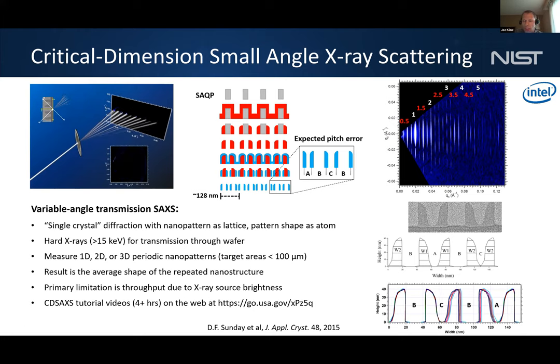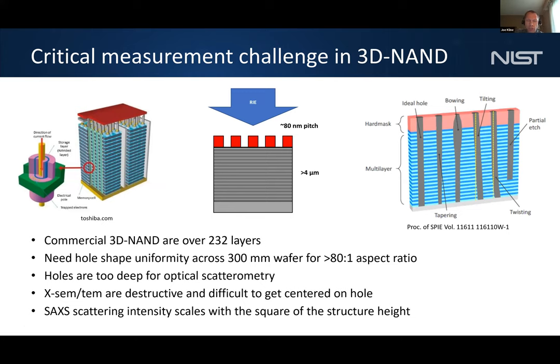To do the same thing in a lab for small structures like this would be too slow to actually commercialize. And so the thing that then happened that was very nice is this was around the time that 3D NAND structures started coming out and they started getting really tall. With NAND, essentially the flash memory that you have in all your solid state devices, they stopped shrinking it about 10 years ago and started going vertical. And so they create these several micron tall stacks, and then they do a very high aspect ratio etch to make what they call the contact holes.